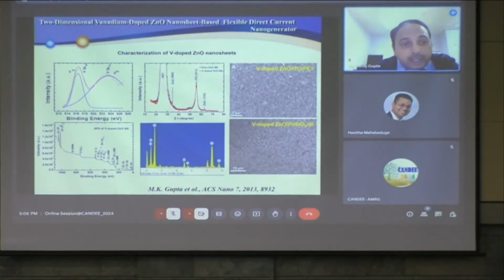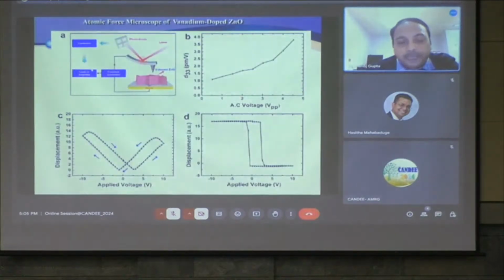Now we also confirmed in which electronic state the vanadium was, V4+ or V5+, whether it is within the nanosheet or on the surface of the nanosheet. So we found that the V5+ ions were within the nanosheet and V4+ was on the surface states. Now, whether the nanostructures showed improved piezoelectricity compared to pristine zinc oxide